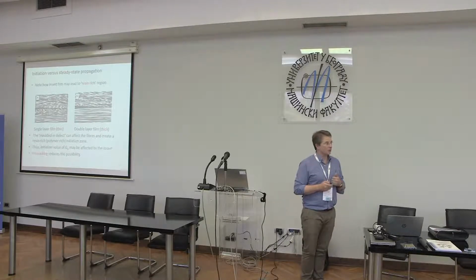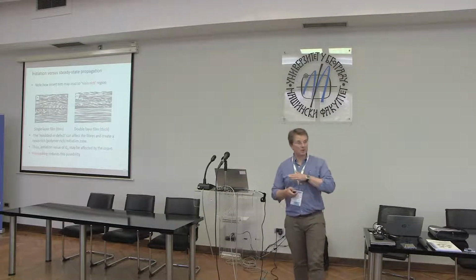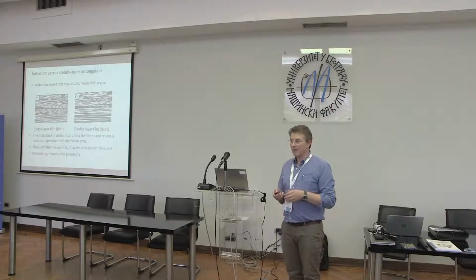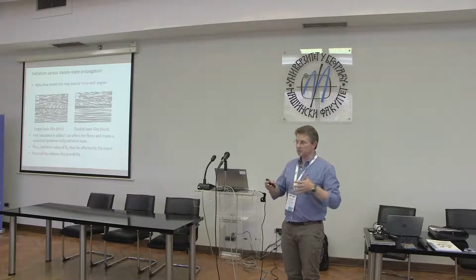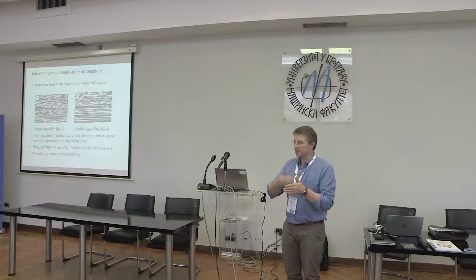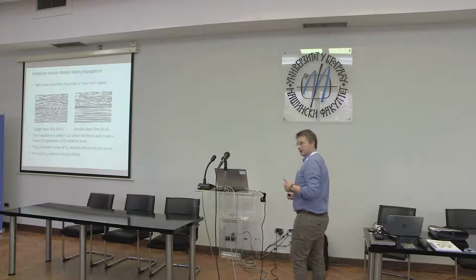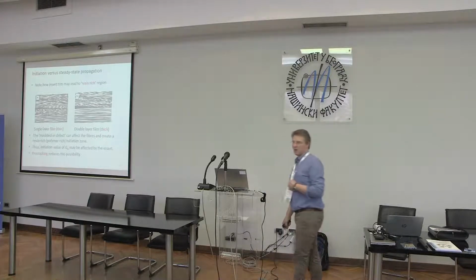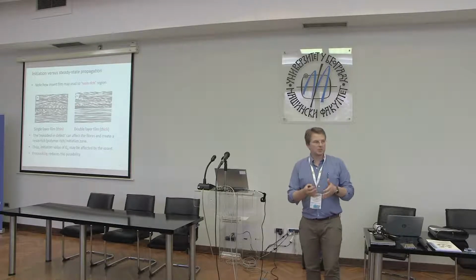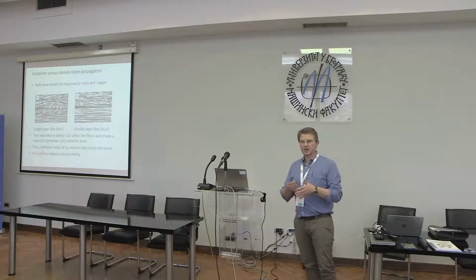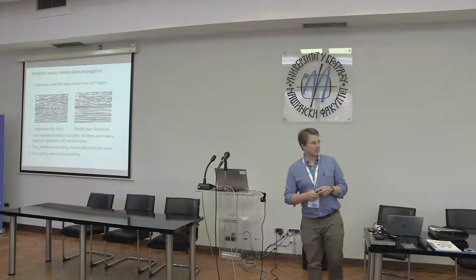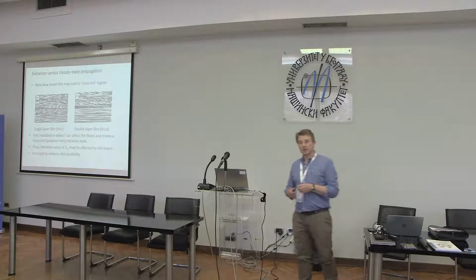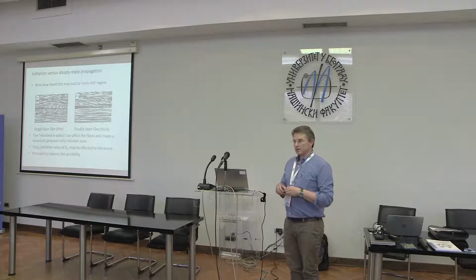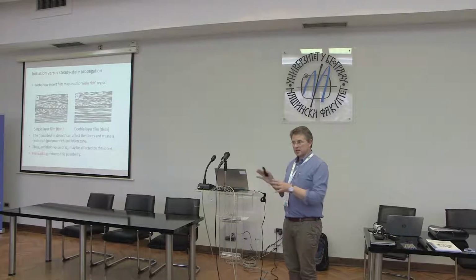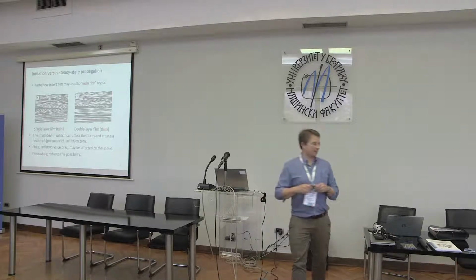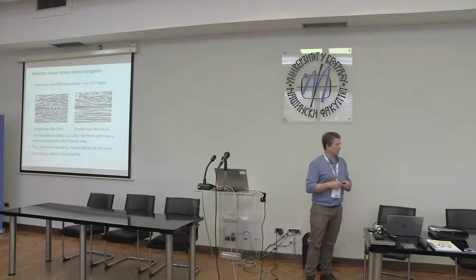Okay? So this is a problem because if we embed a film into the material and by embedding the film in we displace the fibres, we have a big resin-rich pocket ahead of our initial crack. What we would then expect is the fracture toughness to be that of the resin, not that of the composite, when we get our initiation value. Okay, so we could have suspect initiation values. Now, does this matter? So this again depends upon our philosophy.